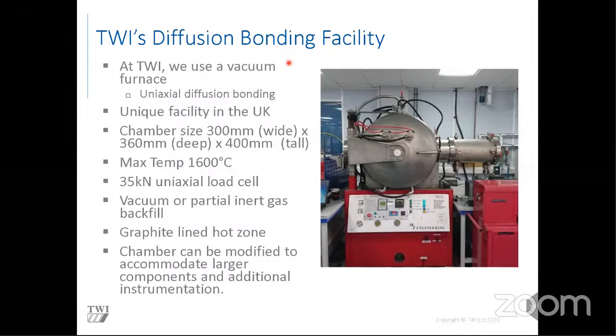How do the surface oxides dissolve? Basically, I'll go into this slightly in another slide, but the temperature at which we carry out diffusion bonding is such that it's high enough energy to dissolve the oxide into the parent material. For certain grades of material, as I will discuss - aluminium being one of those - the temperature of diffusion bonding is not high enough to dissolve the oxides, and oxides is a really big challenge, so I will go into that.